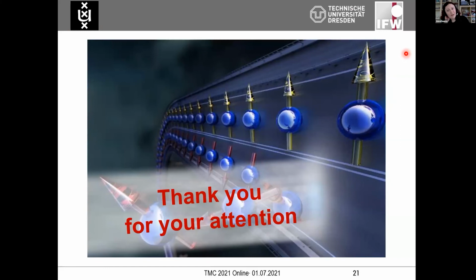Thank you very much for this very on point question. Indeed, control of this layer sequence becomes increasingly difficult. So to your last question, if we can control that and if we know that, I can tell you that we know that on certain length scales. So we always study the samples by X-ray diffraction, showing us the periodicity of the crystal lattice. So let's say for small single crystals on the scale of hundreds of microns, we know that there is very little disorder, or let's say macroscopically this crystal is still a very well ordered lattice. So even if there are some defects, some occasional skipping of the layers and so on, they're very low in number.